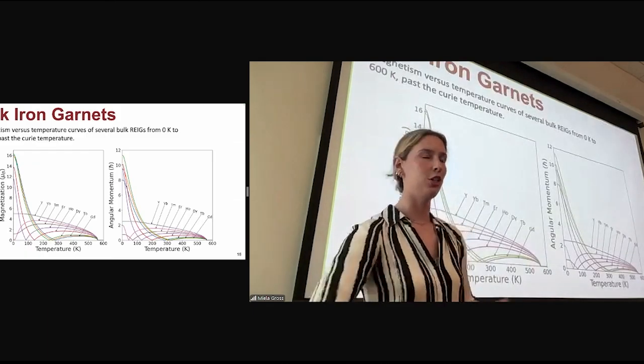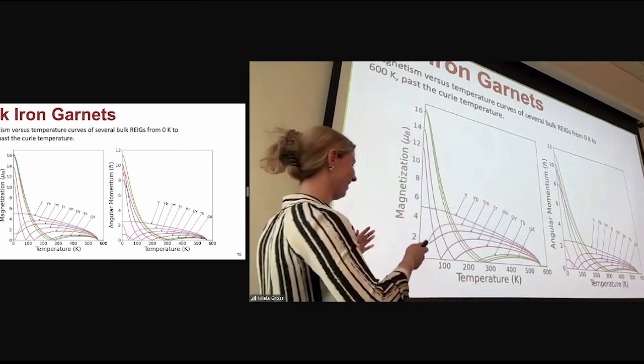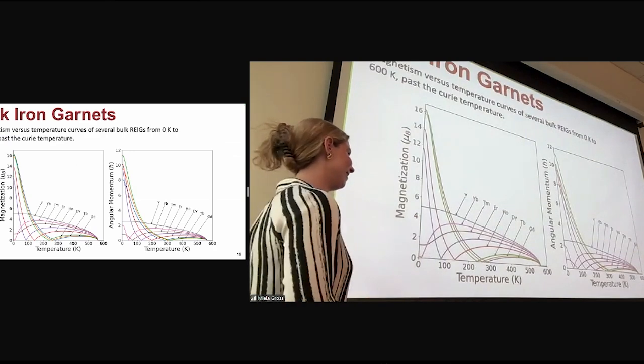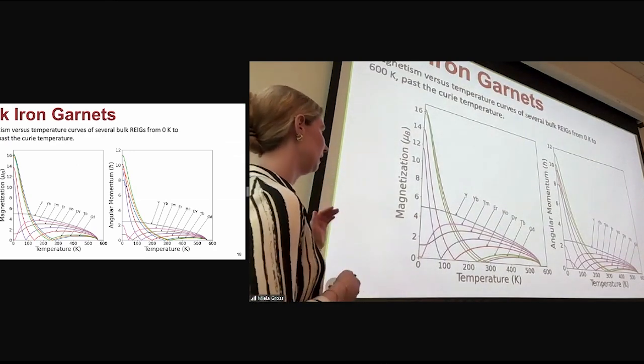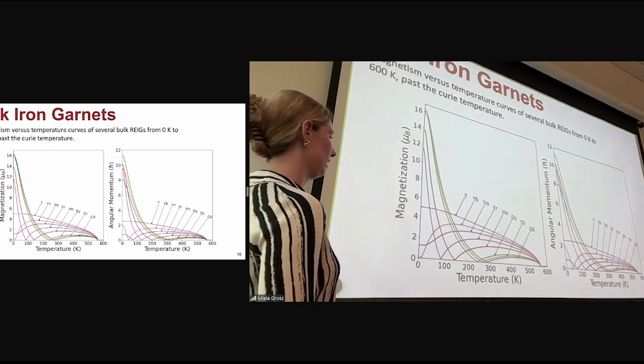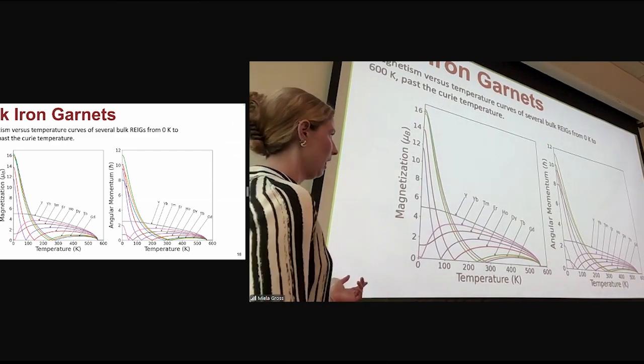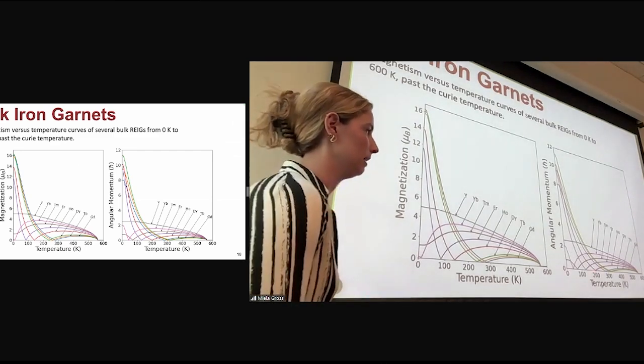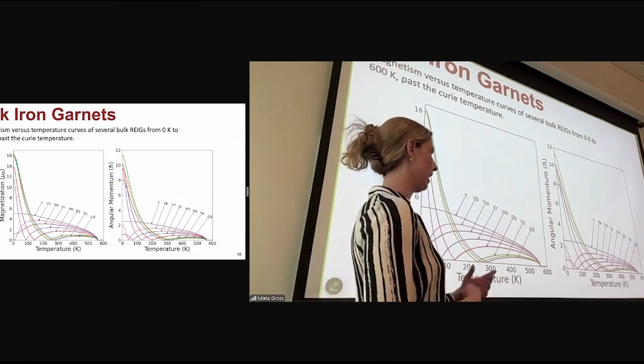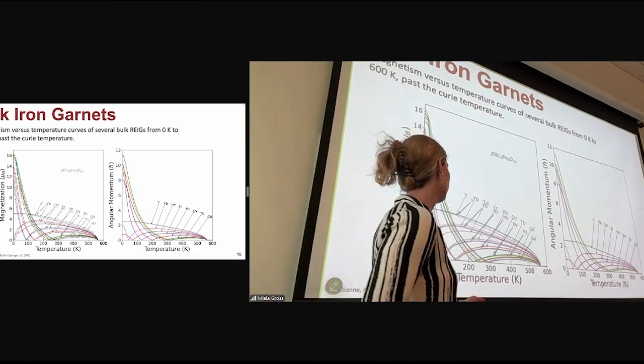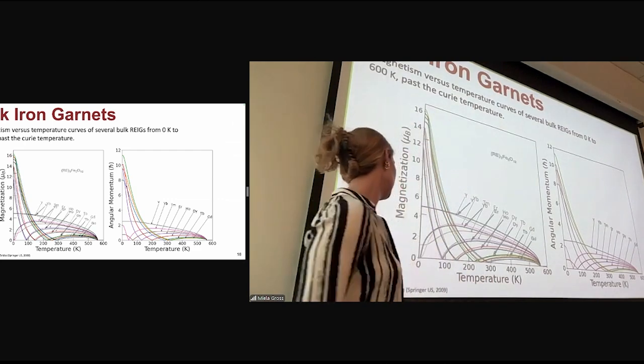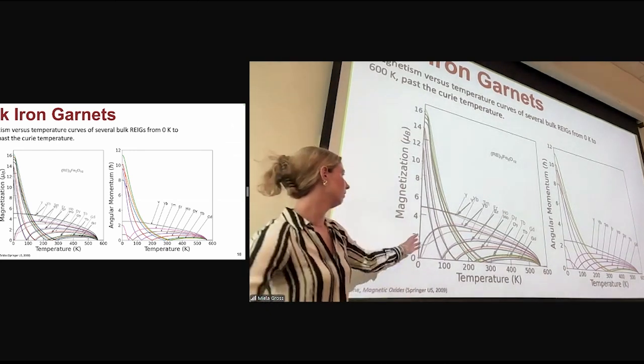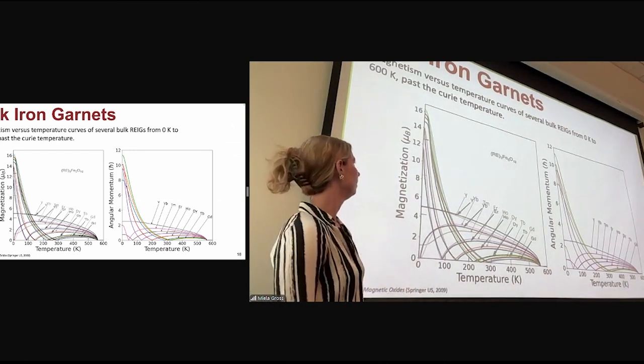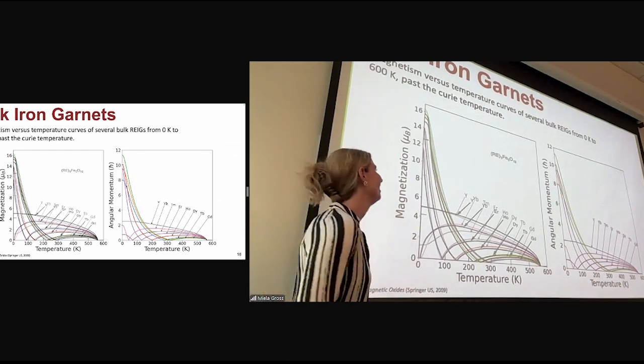So to showcase the accuracy of this model, I basically modeled a ton of different rare earth iron garnets as a function of temperature, and then also their angular momentum as a function of temperature. And to showcase the accuracy of this, I overlaid a little snippet from Dionne's magnetic oxides book. And you can see it fits pretty well.